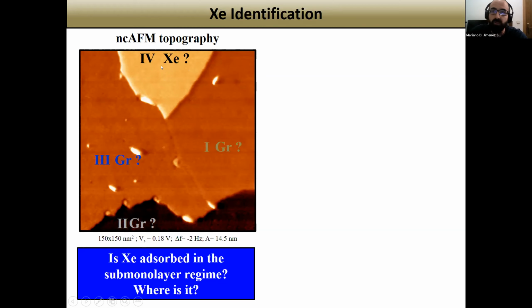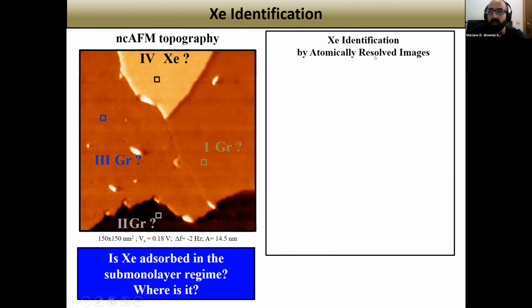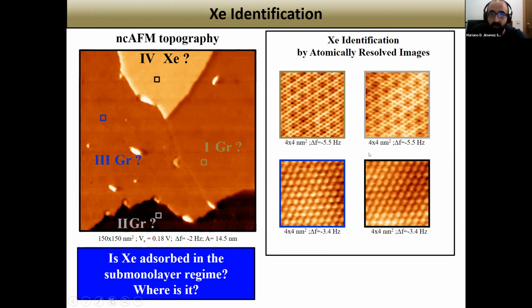Well, in order to verify that, we have acquired atomically resolved images in this square marked region. And we have obtained this. The mark of the images, the color, indicates in which region they have been acquired. I mean, this black indicates that the image corresponds to this region. If we look at these images, we can find clear differences, like the presence of a moiré pattern and a difference in the lattice periodicity, the largest one being the xenon periodicity. Attending to these differences, we can distinguish the graphene areas from the xenon region.